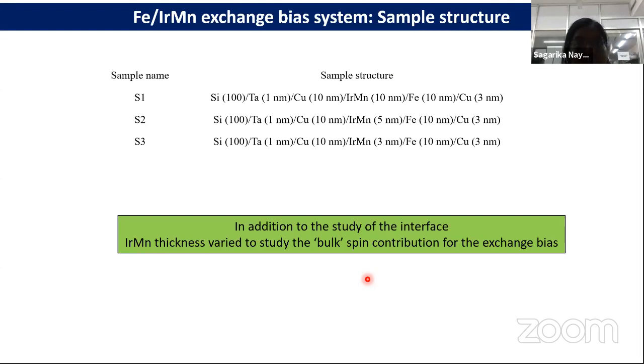So we first decided to study this iridium manganese system, because iridium manganese systems possess very high blocking temperature, but there are many reports that suggest that the iron grows epitaxially on MgO substrate. So now we plan not to do any deposition on MgO, but on silicon substrate. But there is a large lattice mismatch between silicon and iridium manganese, where iridium manganese is the antiferromagnet. So we decided to deposit tantalum and copper as seed layers to remove the lattice mismatch.